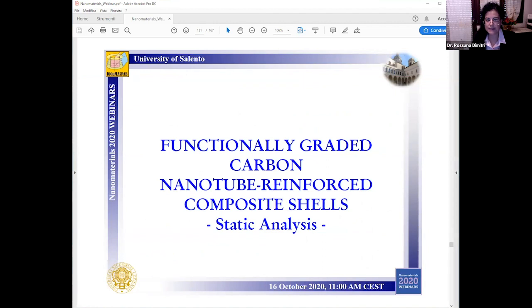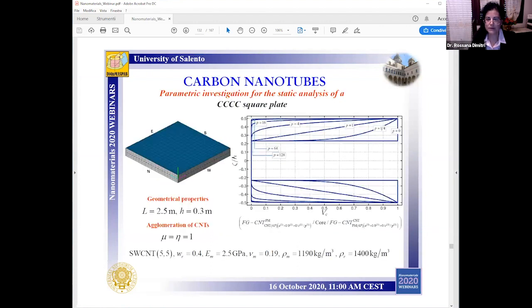structures. And in this last part of the webinar, I will show you some results from a static analysis for some nanocomposite structural elements, where we want to evaluate the through-the-thickness strain, stress, and displacement response by means of a recovery procedure in depth. So let's start considering a completely clamped square sandwich plate under a vertical loading distribution on the top surface. And the sandwich structure has a soft core made of polymer matrix without carbon nanotube inclusions.